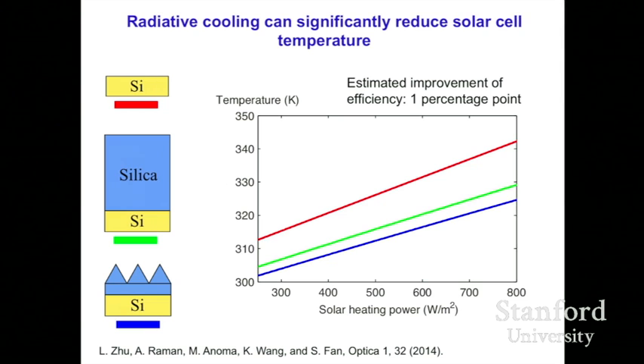And there's another 5 degrees Celsius gain to be had if you replace the silica flat layer with a structured silica layer. So the efficiency improvement estimated, if you can lower the temperature by this much, would be more than 1 percentage point, which is very significant in the context of silicon solar cell.